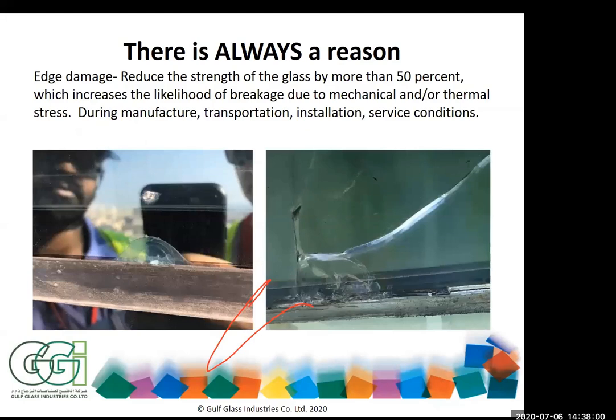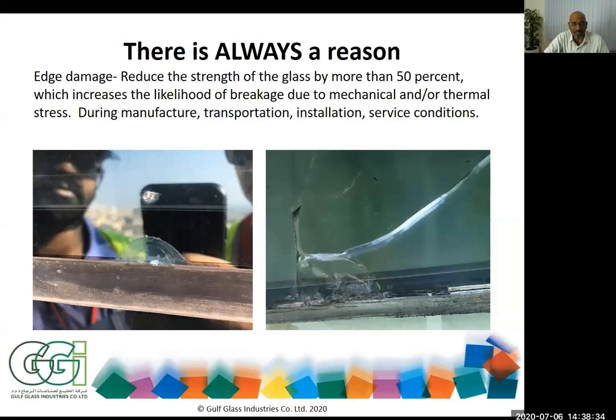So let's look at where we start. One of the major reasons for glass breakages in our experience, and we have been collecting data as GGI since 2005, is that most of the damages, edge damages, are the main reason for spontaneous breakage of glass. The edge damage reduces the strength of the glass by nearly 50%, and this increases the likelihood of breakage due to mechanical or thermal stress. These edge damages can happen during manufacture, that is processing, transportation, installation, and service conditions.